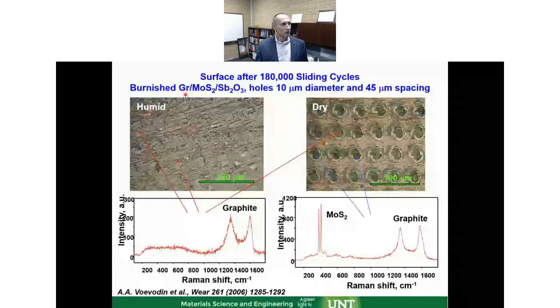Now we put this chameleon coating on the surface, which is based on carbon, molybdenum disulfide, and antimony. This chameleon coating was developed by Jeff Zabinski, Andy Korenyi-Both, and Tribologix. I had a chance to work with them on this, and we combined the laser texturing and this chameleon coating, and we're running it in humid and dry conditions. You can see the dimples, and you can see the partial coverage of these dimples. Importantly, using Raman techniques, we can confirm that in a humid environment you have graphite providing lubrication. Once you change the environment to dry, you start seeing molybdenum disulfide. The molybdenum disulfide oxidizes in humidity, so it starts disappearing or diminishing.